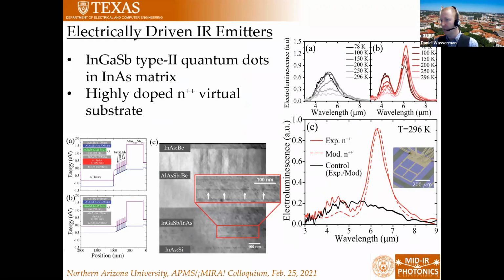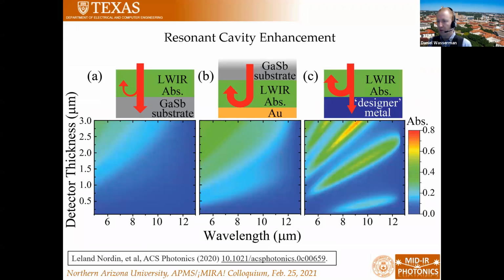In fact, you can see that over the course of going from essentially liquid nitrogen temperature to room temperature, our plasmonic LEDs, this plasmonic resonance or this enhanced resonance doesn't actually decrease much. At best, it's maybe a factor of 2 we lose in this peak, but in the control device, we lose most of our emission. It's pretty noisy by the time you get to room temperature. So some of these devices do work at room temperature.